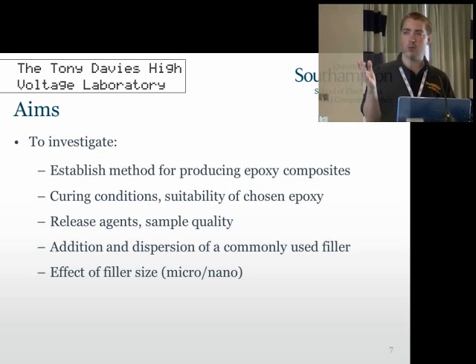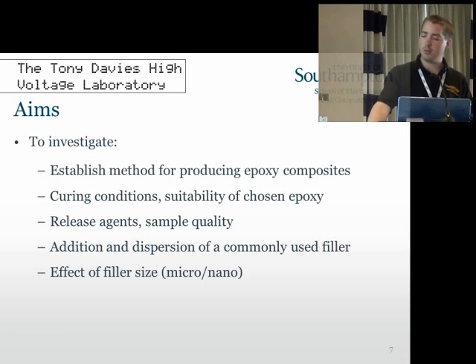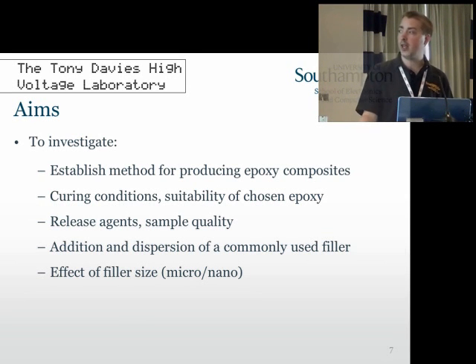So the aims and sample production for this investigation. The aim was simply to establish a method at our lab for producing such epoxy composites, define the curing conditions and the suitability of the epoxy that we started the investigation with, have a look at any release agents and the sample quality that we were producing, and then add and disperse just a standard commonly used filler as a first stepping stone on the way towards producing better insulating materials.